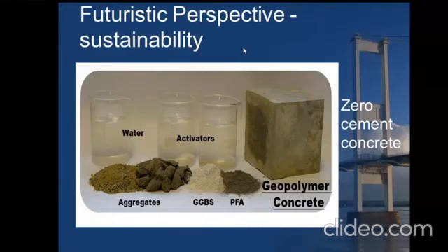The major factor that is governing the strength is the molarity of sodium hydroxide and the sodium silicate by sodium hydroxide ratio, right? So this is one of the things, I should say, still it is in research with a lot of durability practice and all those things, but there are a lot of countries which have adopted it, mainly Australia. Nowadays, many bridge tunnelings, bridge structures have been constructed using this geopolymer concrete. They have actually perfected the activator solution there. So here you can simply order a bag of material which contains all these binding material along with a combination of fine aggregate and coarse aggregate and the alkaline activator, which is supplied in cans or barrels. Take to the site, mix it, and because now they have come across, you don't need temperature curing for making a geopolymer concrete. You can even make it in a normal ambient curing temperature.